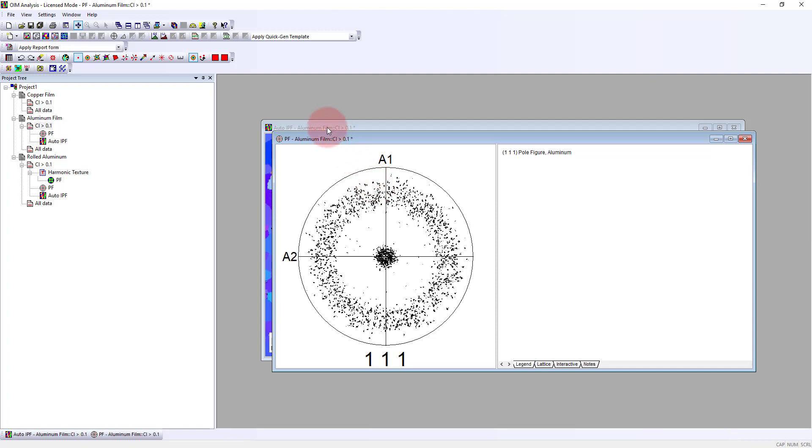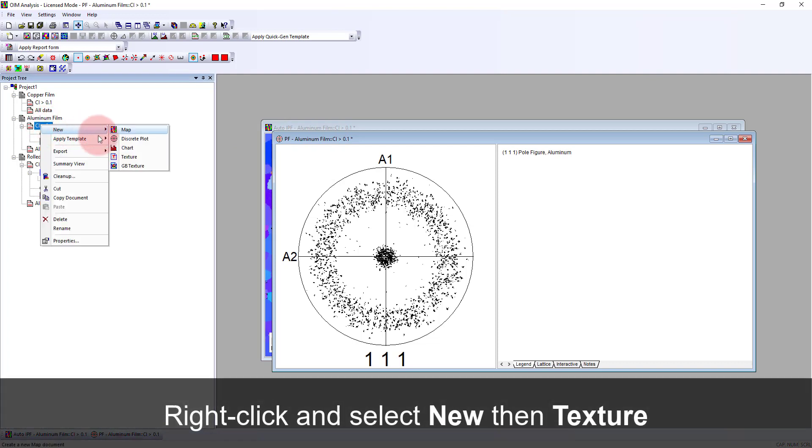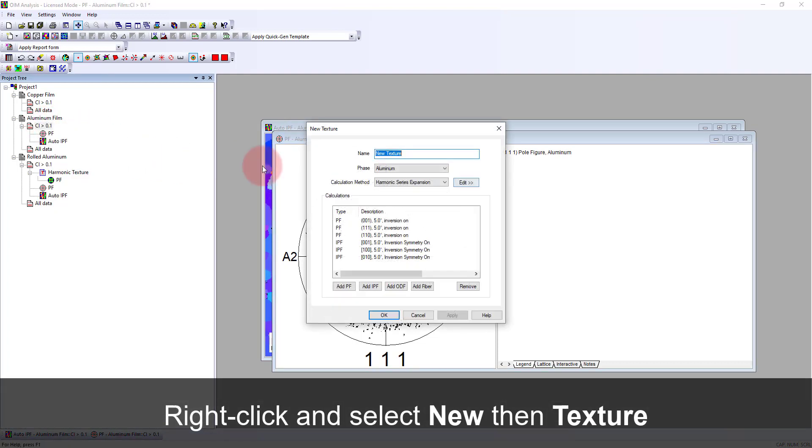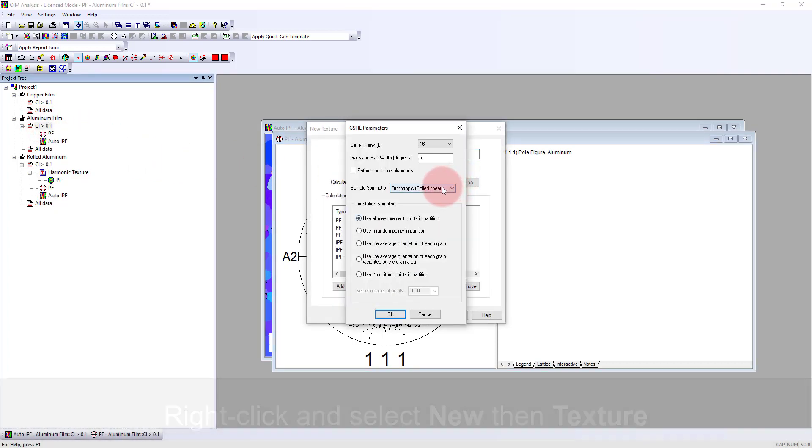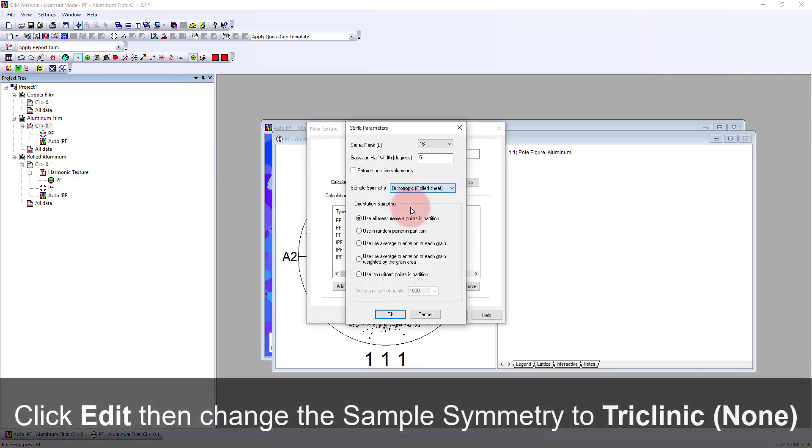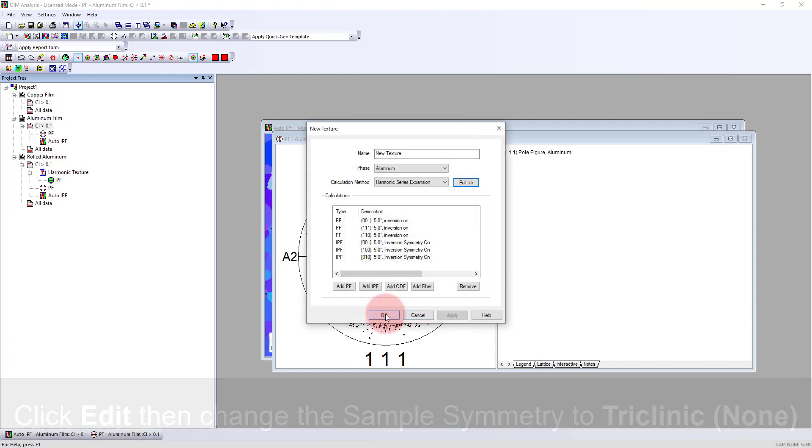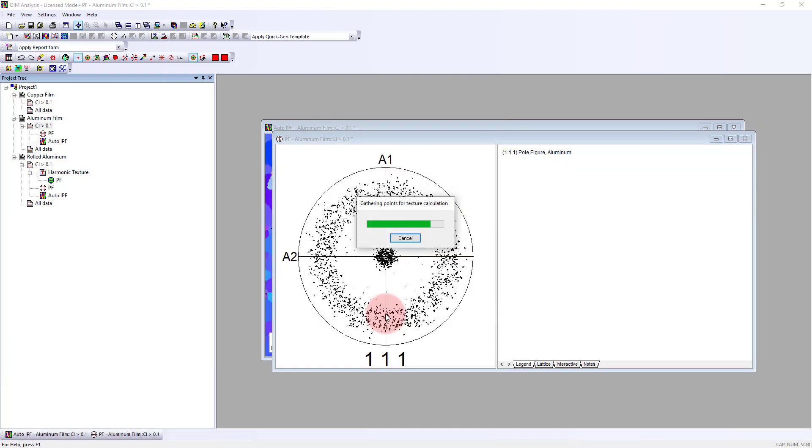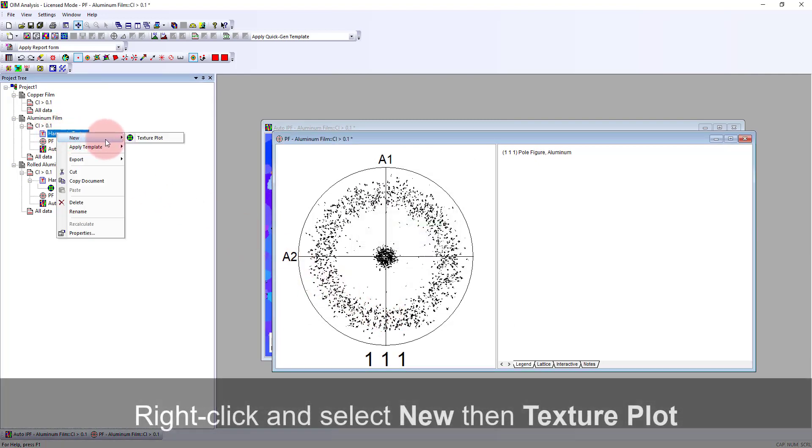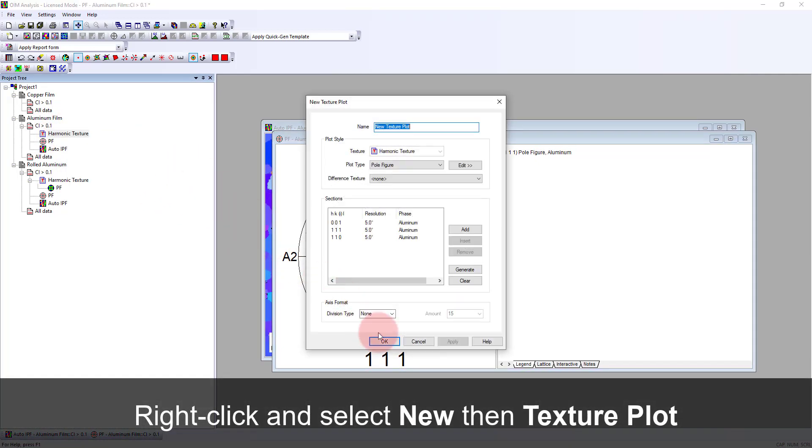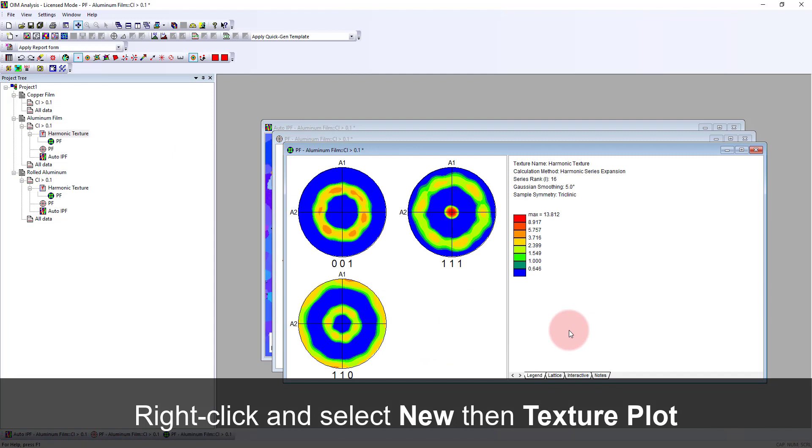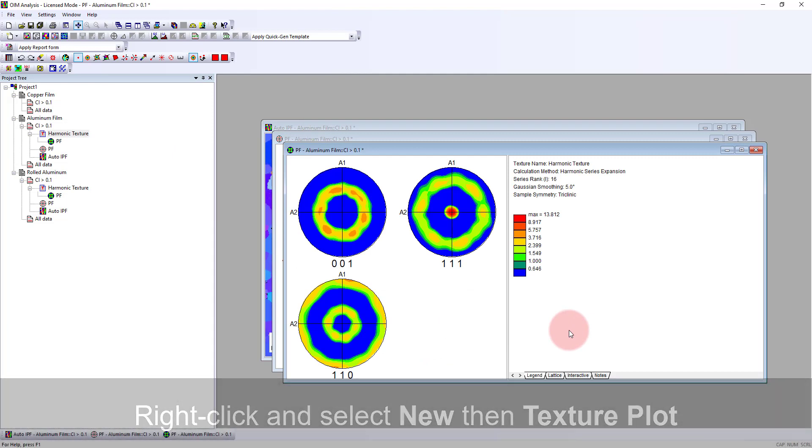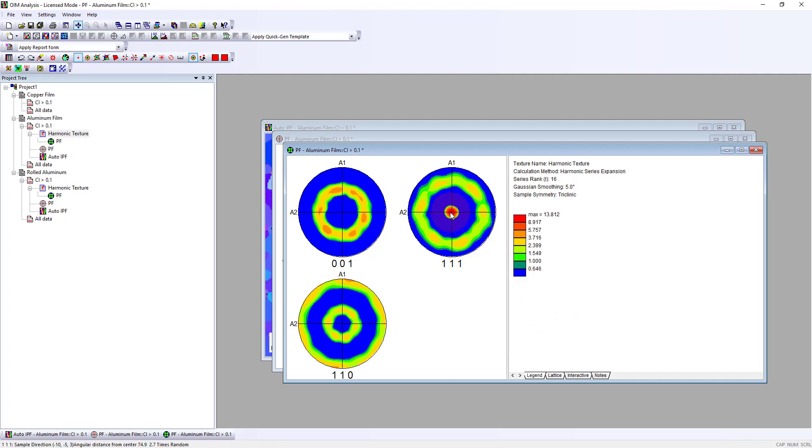If we look at the same thing and calculate a texture here, in this case I do not want to have the rolled sheet on. I want to go to none and calculate our texture for this. We will see that it's a pretty consistent fiber texture. It's pretty even in terms of density along there, but it's stronger in the center because all the orientations are in this direction, weaker here because there are fewer orientations at each point. That's what we call a fiber texture.